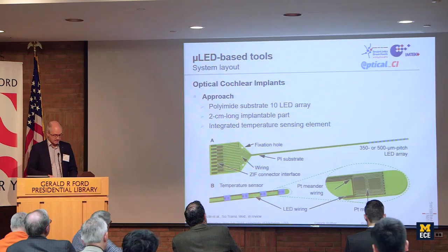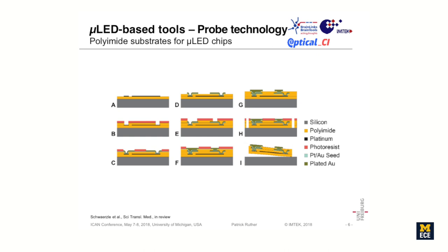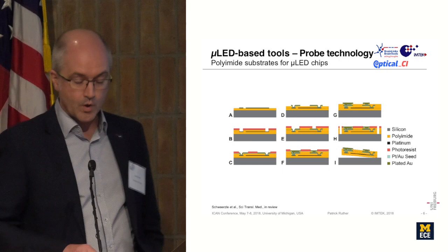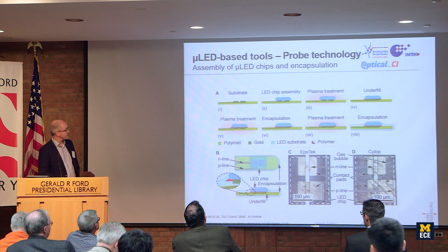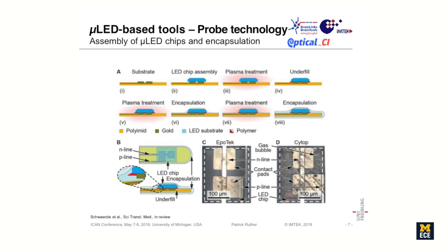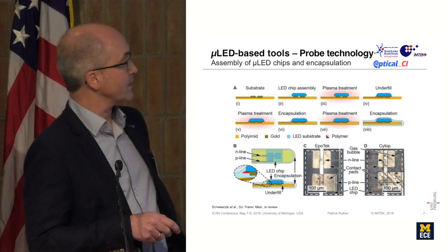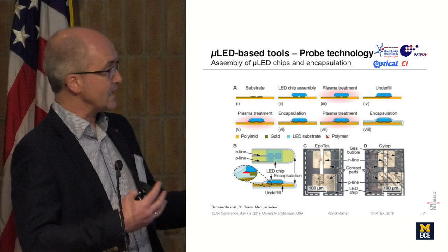The fabrication process is straightforward. So we use the polyimide process that Thomas Stieglitz introduced in Freiburg. We modified it a bit by electroplating the metal tracks to reduce the line resistance to operate our devices at reasonable voltages. And we also include electroplating of the contact pads so that the assembly of our LEDs is easily done using the flip chip bonding process as briefly sketched here. So we start with our polyimide substrate, the electroplated pads. We do the flip chip bonding, a plasma treatment, and we have to underfill the gap between the LED and the substrate to isolate the contact pads, then another plasma treatment, and then the entire probe is encapsulated into polymers. Most of the time we simply use silicone.